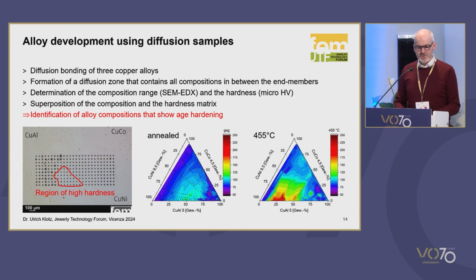The left one is showing the hardness as a function of composition in the annealed condition. And the blue colors indicate that all the alloys are quite soft. Now in the right diagram, you can see that there are areas in red and yellow color.